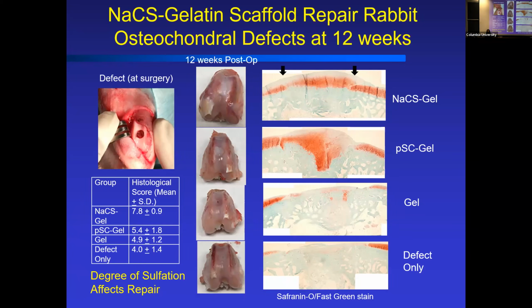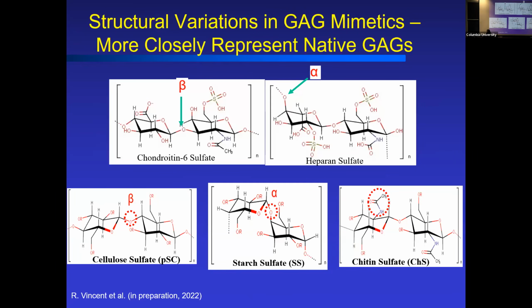So we see here at 12 weeks with the fully sulfated, we're getting that bridging of cartilage across, by that safranin O staining, that orange that's shown there. And you get restoration of subchondral bone, which is that green stain. And so that's a mature growth of cartilage tissue that you would like to see. The other materials, even the partially sulfated, were still at an earlier stage of repair. So very promising work. We're continuing those studies in different animal models to show that we can utilize this for cartilage. And we're currently also working on some variations of these GAG mimetics so that we can more closely represent some of those native GAGs.